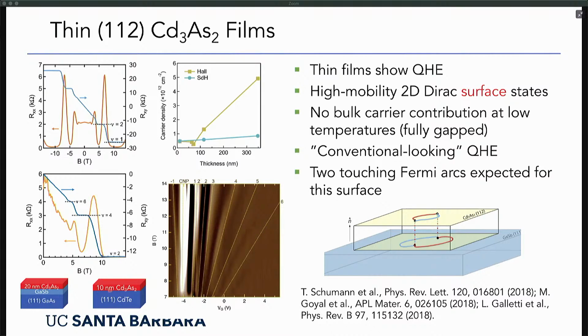These are grown on two different substrates, but they're both 112-oriented. In both cases, the results look very similar. There's a clear quantum Hall effect, and that means there's a two-dimensional electron system. There's also very little parallel transport from the bulk. There's only transport from these two-dimensional states, and these two-dimensional states are in the surfaces.